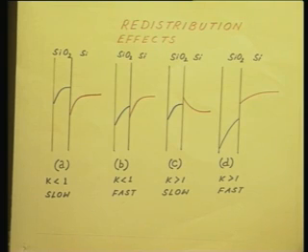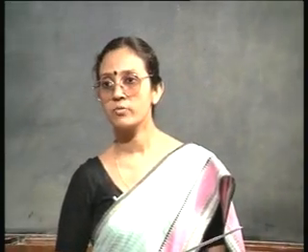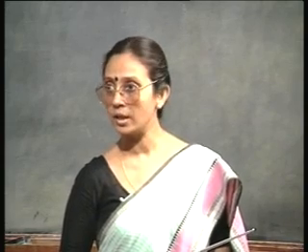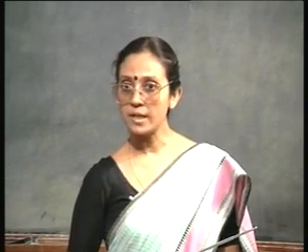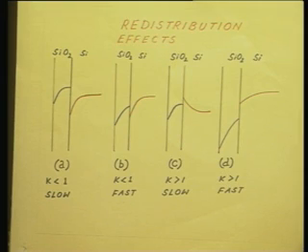An example is boron. Boron in silicon has a segregation coefficient less than 1 and boron is a slow diffuser through silicon dioxide. That is why we can use boron as a p-type dopant. So, what is the situation? Since K is less than 1, the dopant boron will preferentially go into silicon dioxide because its equilibrium concentration is more in silicon dioxide than in silicon.